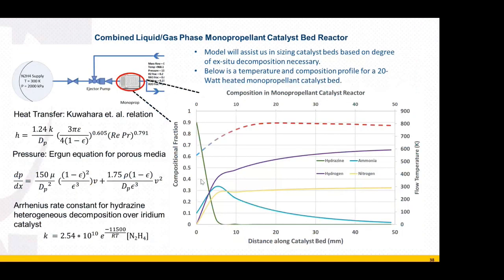Just a quick outline here of the decomposition of gases that are flowing into the SOFC anode. Here you see in the catalyst bed, the hydrazine rapidly decomposing. Here we've modeled this as a nickel iridium catalyst. The hydrazine decomposes and begins to form ammonia, hydrogen, and nitrogen. And so by the exit here, we've tuned the particle size and the heat input. This is a continuous 20-watt heater. By the time we exit the catalyst bed and the gases would be entering the anode, we have very little ammonia left. But we have done studies on ammonia as well, ammonia in the anode, excuse me.